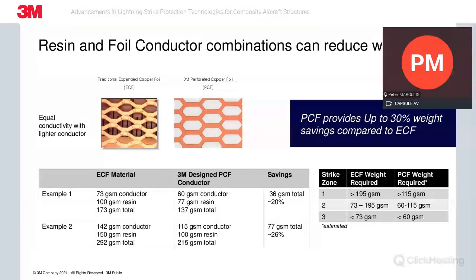Okay. Here we have some examples moving from expanded copper foils to perforated copper foils. The 73 grams per square meter ECF and a 142 grams per square meter ECF are pretty standard materials in the industry. Below them, you will see the weight of the resin and the total system. Then on the right of that, the numbers that you see there for the PCF are what we have designed to be equivalencies to the ECF materials.